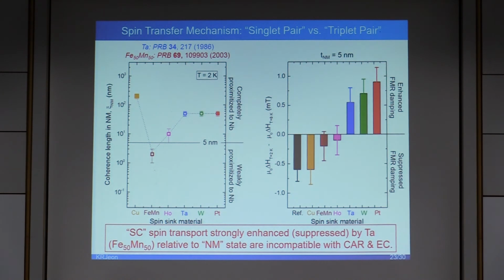Importantly, of the materials used, a 5 nanometer tantalum completely proximity coupled to the niobium layer should be almost fully gapped and so eliminate crossed Andreev reflection and elastic cotunneling, whereas a 5 nanometer iron manganese weakly proximitized to the niobium layer strongly suppresses the niobium gap and thus makes this process more possible. The experimental result, which shows that superconducting spin current is strongly enhanced by the tantalum and suppressed by iron manganese, is incompatible with these processes. Therefore, the remaining possibility is that the spin angular momentum is carried via spin triplet supercurrent.